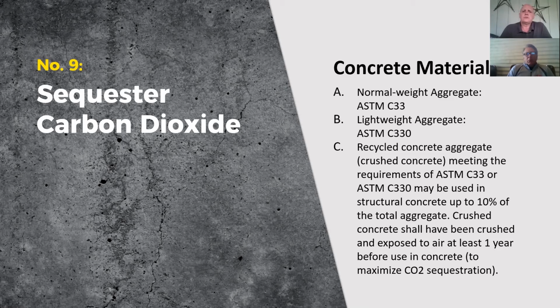You can use recycled aggregate in some structural applications. Usually we've done some testing, and there has been some testing where you could use up to, say, 10% and really not affect the performance of concrete. Now, I'm not talking about using 100% recycled aggregate in concrete necessarily, but using a small portion of the aggregate as recycled aggregate. And then permitting that you at least require all the aggregate base and any fill materials used on the site be from that crushed concrete that's already been exposed to air, which would then sequester that carbon dioxide that it would have absorbed during that period.